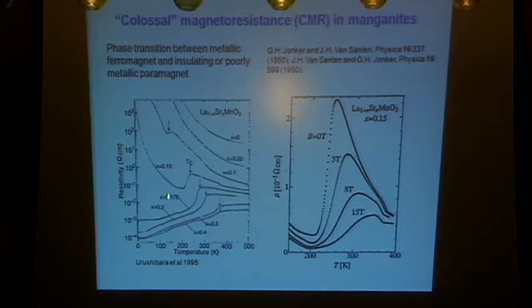And not surprisingly then, if you apply a magnetic field in the vicinity of this transition, you can change the resistivity a lot. Actually, this isn't very much. There are ways of making this effect very, very much bigger. But nonetheless, this was of interest for a while as the possibility of having a very large magnetoresistant effect that one could use one way or the other. I shan't really be concerned about it.